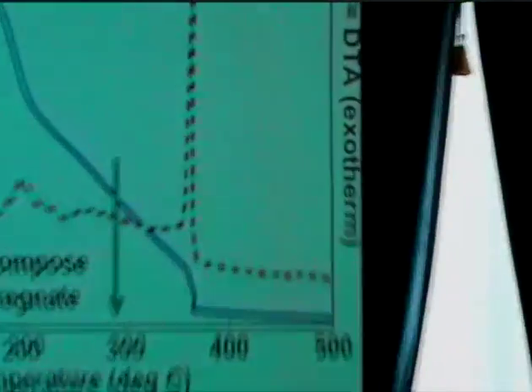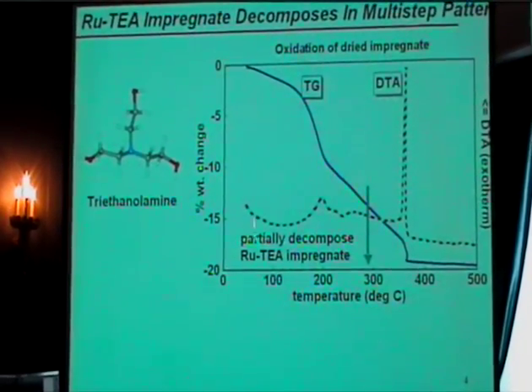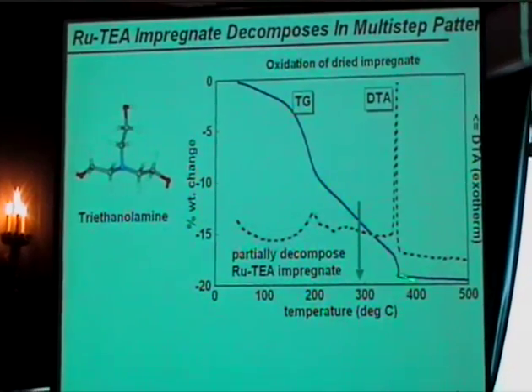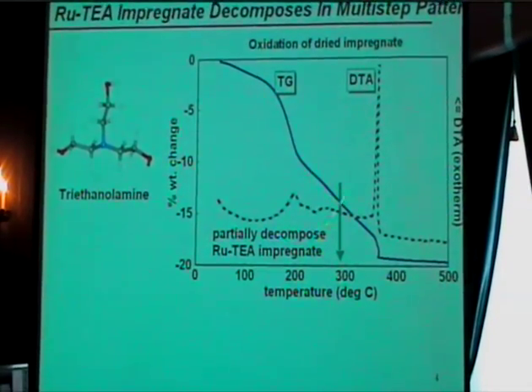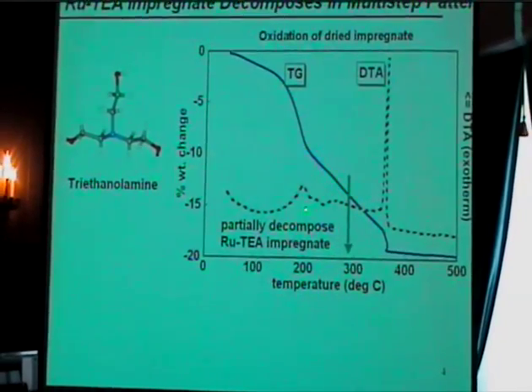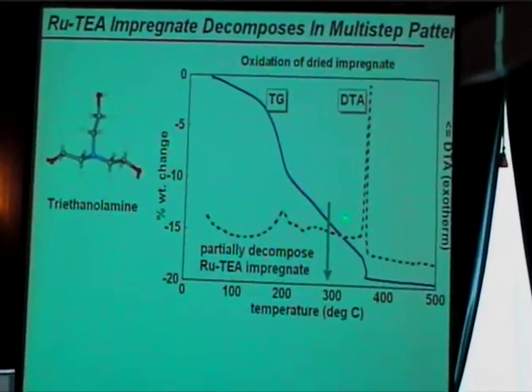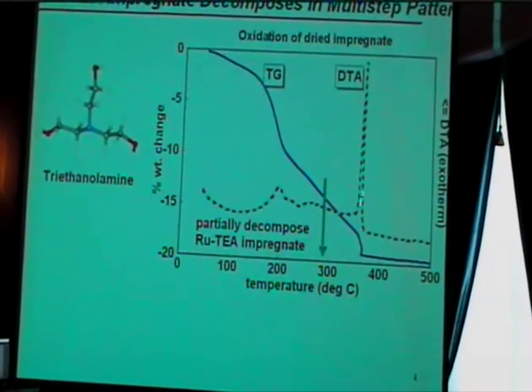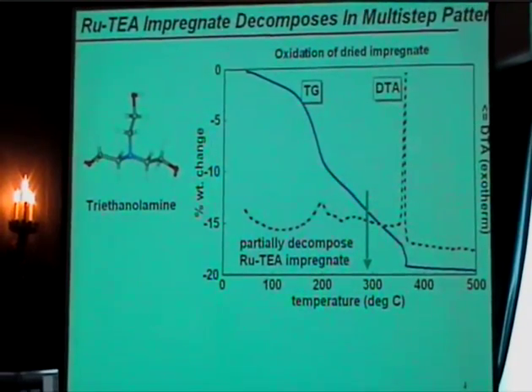And simply, if you take a ruthenium salt like nitrate or nitrosyl nitrate, you put it into just aqueous impregnation and add some of this triethanolamine, and you look at the decomposition of that on silica, you find that it's actually a very eventful process. A lot of things are happening when you just air oxidize it. So here's the weight change in blue, and very interesting, the DTA curve. So we have several exothermic events going on here at lower temperatures, and there's a broader one here. And then there's a very, very sharp one as we go out to higher temperatures. So this is going through multiple steps of decomposition, including some particular complex that's getting formed here as you go through these partial decompositions that are stable at high temperatures.